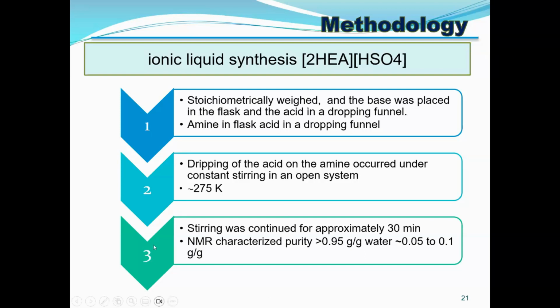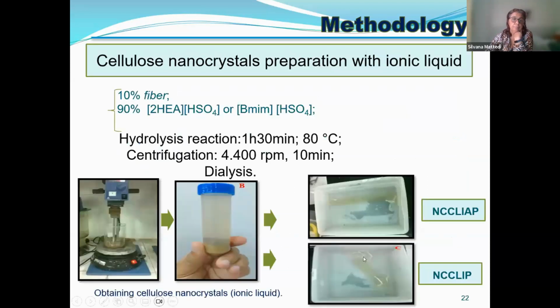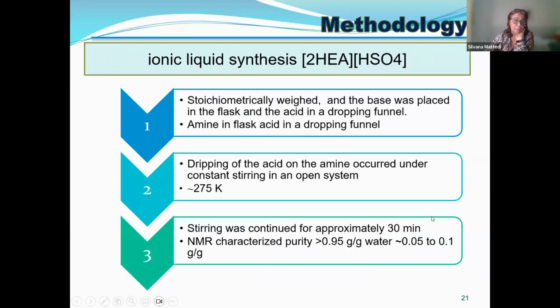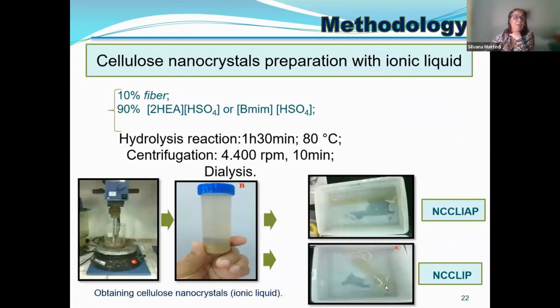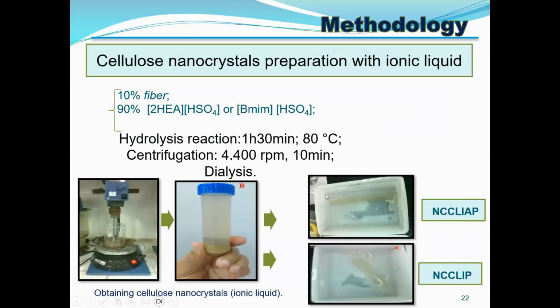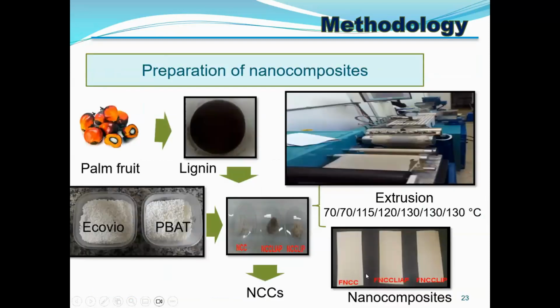So NMR was used to characterize purity. We have a purity higher than 95% and low content of water. It's a high content of water if you compare with other things, but low content for these ionic liquids. If you put it on a molar basis, a lot of water. But then we prepare the nanocrystals with the ionic liquids at a slightly higher temperature. So we have two kinds of nanowhiskers. And then we prepare the nanocomposites.